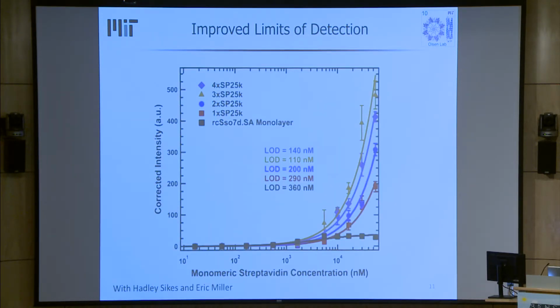Again, you can see improvements in the limits of detection for a monolayer versus the different binding proteins, with tetramer, trimer, dimer, and monomer. We have the lowest limit of detection for the trimer, which interestingly is the one with the highest degree of ordering in the nanostructured material. This suggests interesting relationships we don't understand yet about controlling nanostructure, transport, and ordering that can allow you to produce decreases in the limit of detection in these sensors.